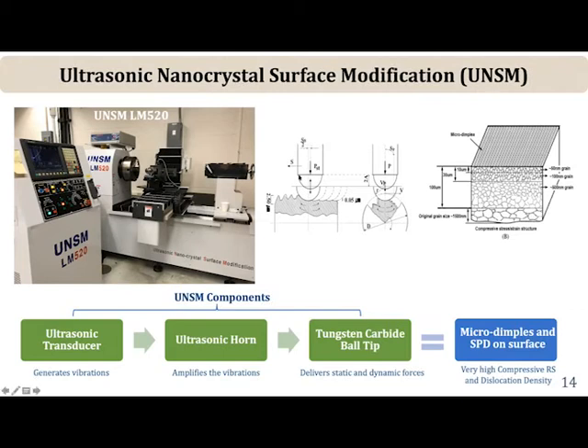The difference is in low plasticity burnishing, you keep the tool pressed and then you move it along the surface very slowly. Here, you not only have a static force, but you also have a dynamic force whose amplitude can be controlled. So the main variables in this process are the amplitude, that means the depth to which you hit it, and the feed rate, the rate at which the tool traverses, and then the static load is another variable. So the machine itself is relatively simple. This is the one at UC.